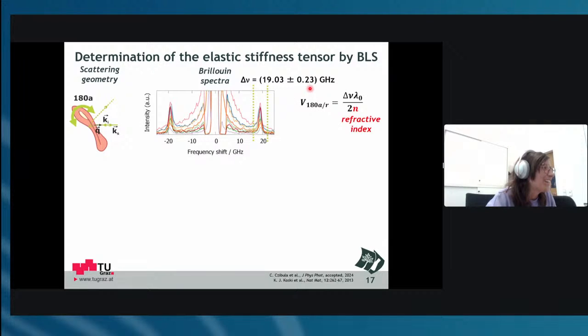But then reality hit. When you want to go from this geometry to sound velocity, you need the refractive index of the fiber, and that is, as I figured out, quite a mess. With the heterogeneity of the material, to really determine it nicely on the micro scale is, I don't know, not feasible. I tried a few things. You can also do it with Brillouin, but I just get huge scattering. So this is still work in progress.